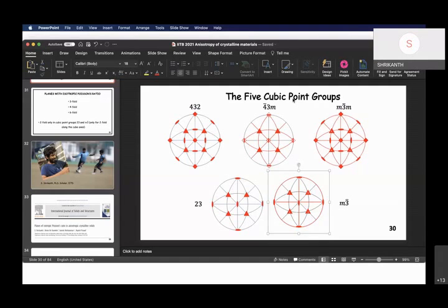Final closed-form expressions I've been able to derive for cubic, tetragonal, hexagonal, orthorhombic, and one other, these five. For all these cases, are you guaranteed to get something? Not always guaranteed. In all these cases we have the symmetry planes, so those are guaranteed. But orthorhombic, you can have orthorhombic materials with no isotropic loading directions.